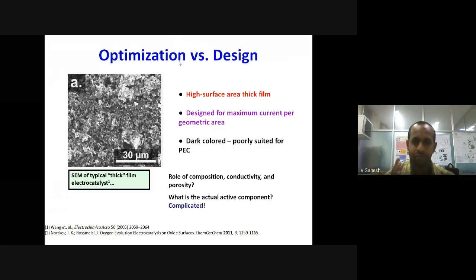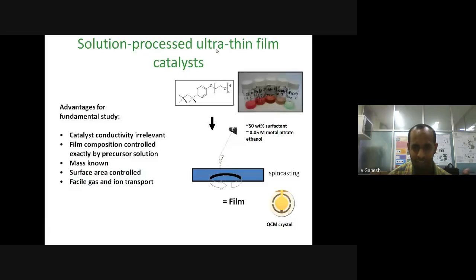Now, maybe one critical parameter in terms of catalyst development I want to discuss. Always, what we do is we prepare a material and we disperse the material in a solvent and drop cast on the electrode surface to study the role of this catalyst for ORR, OER, or HER, etc. Now, you need to find out the optimum thickness of your coating, which is a very critical parameter. You need to do this through a trial and error method. How thick your coating could be, because if your coating is thicker, then it can lead to large capacitance rather than electrocatalytic activity. Okay, and of course many different parameters like conductivity, accessibility of the area, etc. matter. In the case of homogeneous catalysts, okay, the thickness of the film also matters. So that's what it talks about.